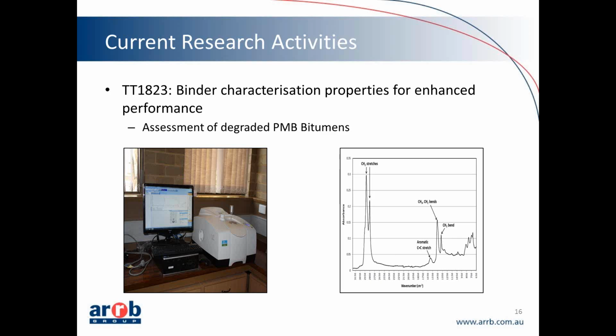Now, what we found as a result, and we did 2 lots of asphalt testing, fatigue and wheel tracking, and I'll discuss the fatigue now. With the high polymer modified binder content, we found that through heating there was around about a 10 times increase in the fatigue performance, and for the low polymer content we found that there was about a 5 times increase. So that's some interesting research and results that we've got as a result of doing that testing.